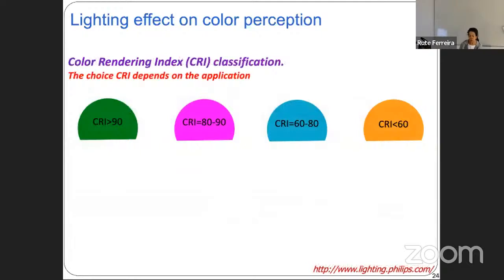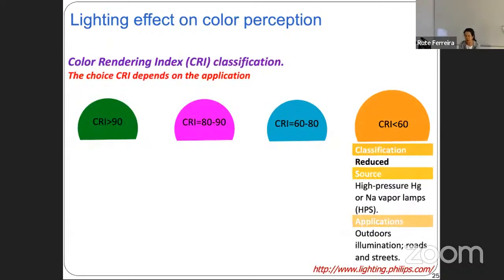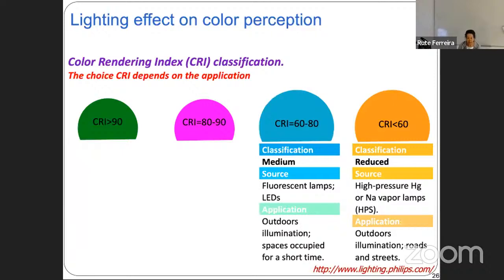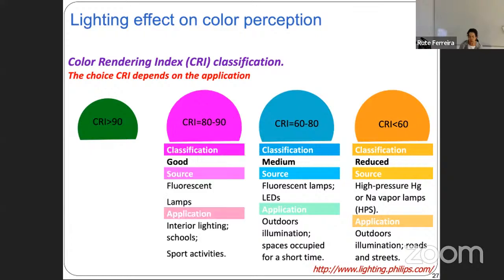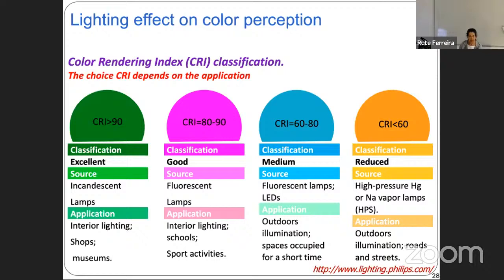So let's see how to choose a CRI depending on the application. Typically, reduced values below 60 can be found in high pressure mercury or sodium vapor lamps. You can find them in outdoor illumination, roads and streets. A medium CRI can be found in fluorescent lamps and LEDs and is applied in outdoor illumination or spaces occupied for a short time. A good CRI between 80 and 90 can only be found intrinsically in fluorescent lamps. It is ideal for interior light, schools and sport activities. And finally, the excellent classification, CRI above 90, can be found in incandescent lamps, and it is ideal for interior light, shops and museums.